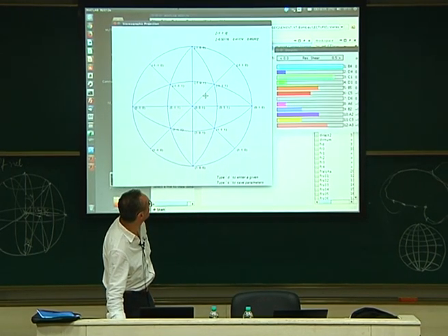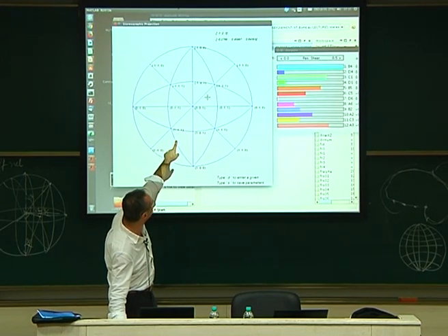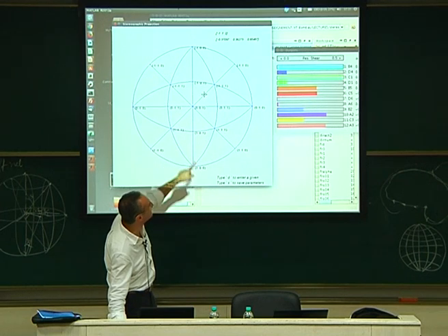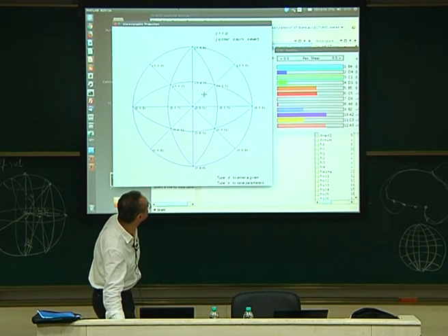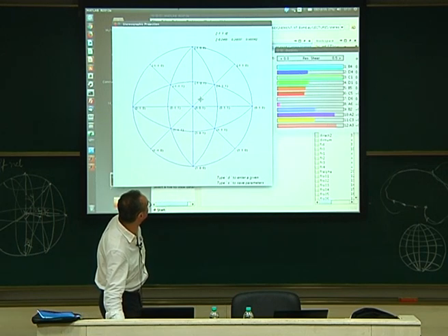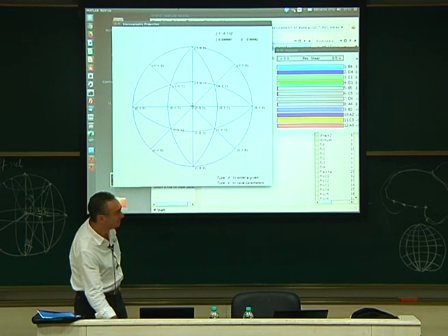And if I go toward the boundary, it will move toward the Burgers vector, which is bar 1 0 1, and simultaneously a second one becomes active, which is C1. B4 and C1 are active. Now if I go back here, you will see that you have the 8 systems active again, and 0 between. 8 systems are activated.